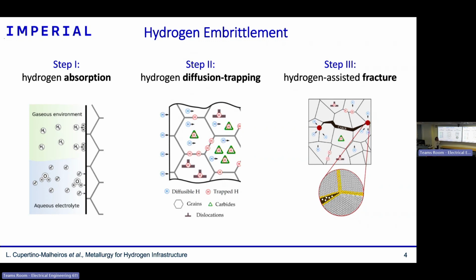So the third step, and actually the one that has more engineering relevance, is how this phenomenon, so hydrogen moving inside of the alloys, interacting with the structure, at the end will actually cause fracture, failure. And that's what we are talking about when we talk about hydrogen embrittlement. It's hydrogen getting absorbed, moving inside of the alloys, and resulting in cracking, in failure of the structures.